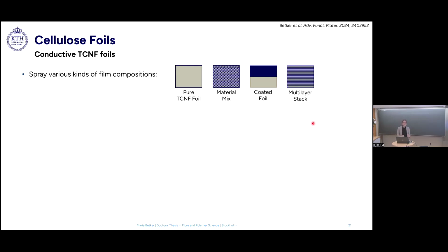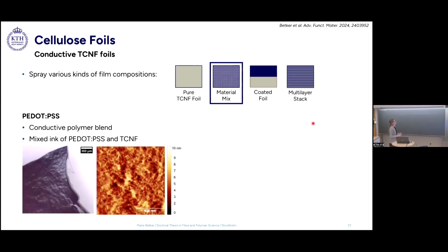You can make various different kinds of film compositions. Here, for example, this is a material mixed foil. We took PEDOT:PSS, a conductive polymer blend. I will go into the details later, but for now, it's only important that we have a conductive polymer and the TEMPO cellulose, mix it together in water and spray this mix directly. This is how we made these conductive foils.